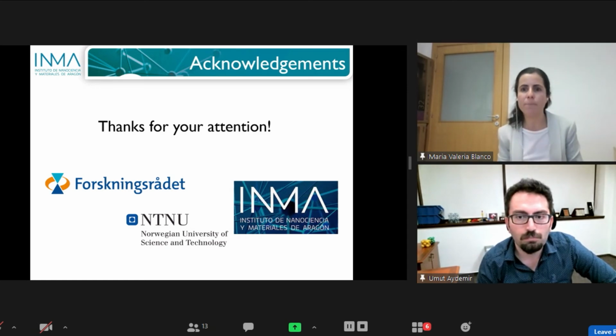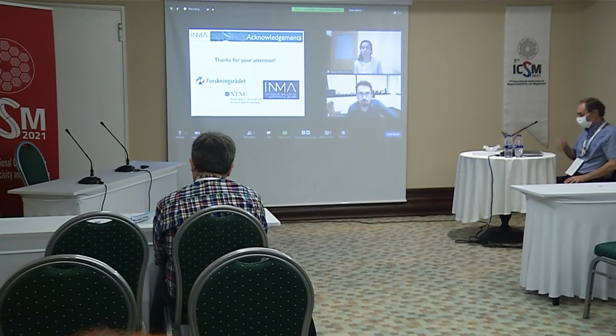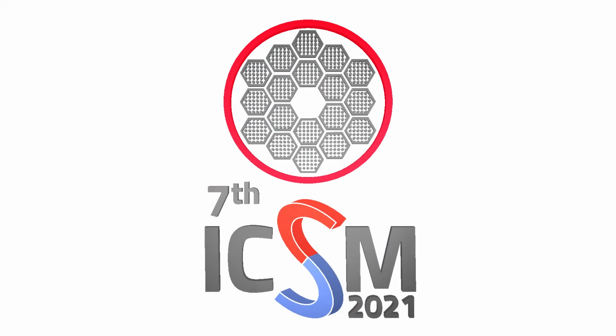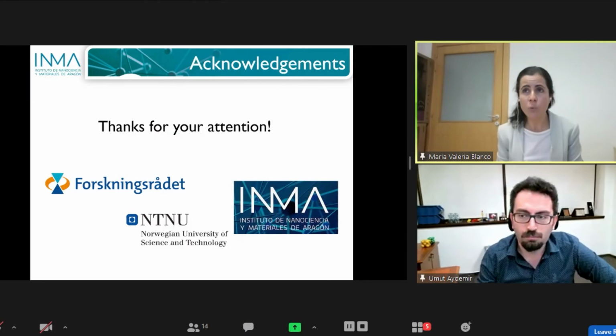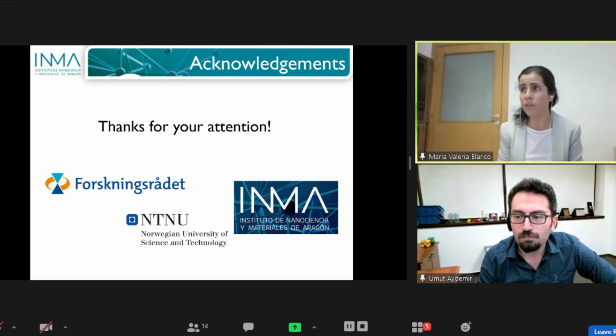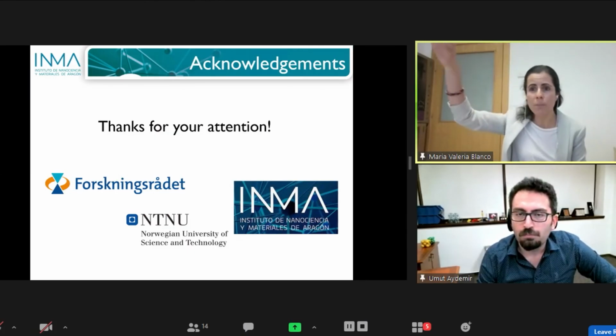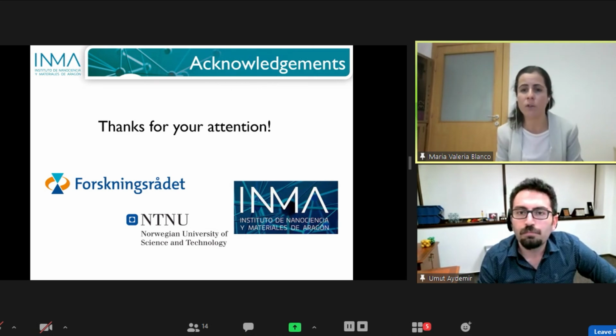I have another question. It's well known that 100 cycles is not enough for modern batteries. Did you try to cycle for more than 100 cycles? That's what we are doing right now. Up to 200 cycles, it's quite stable, and then after 200 cycles we are observing a bit of decay in the capacity, but not so much until now. But we haven't performed higher cycling.